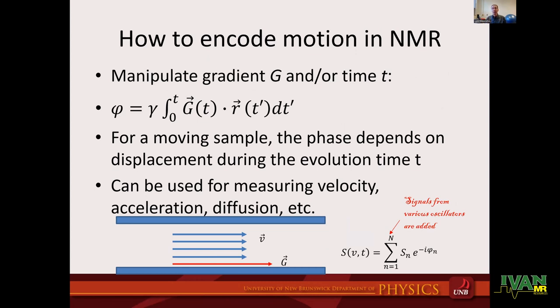So to measure the response, we need to encode sample velocity. And in NMR, we typically do that by manipulating the applied magnetic field gradient or application time. And by this, we can then encode the phase with information on displacement. And then we can extract that information, right?